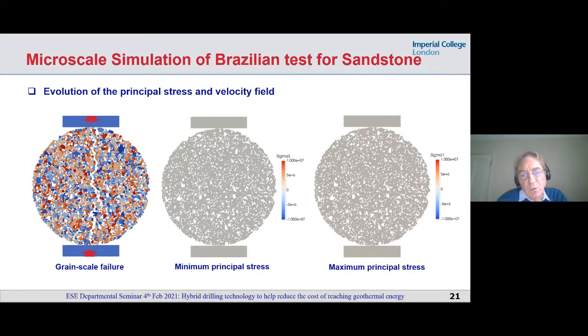Now we're focusing on the middle simulation, and this is where I'm going to show you the minimum principal stresses. Now these will be the tensile stresses that will develop in the sub-horizontal that will pull the specimen apart, and we'll see this tensile stress chain phenomena growing, intensifying in the middle, then snapping, and then the crack propagates and the tensile force chains and stress chains move up towards the top platen, and you see this beautiful dynamic shaking of the specimen just before it falls off.